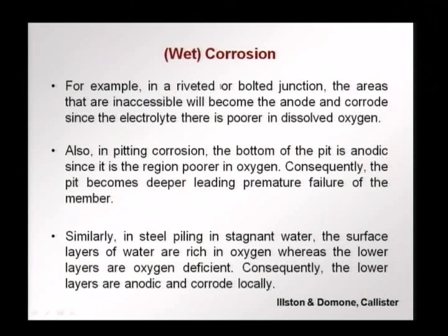Similarly, we find in sheet piling with steel in stagnant water, the surface layers are richer in oxygen, whereas the lower layers are oxygen deficient. So, what we find is at the top we need not see any corrosion occurring, but just below the surface, not very much below, but just below the surface where you have lesser oxygen, the layer of steel becomes anodic and starts to corrode locally. So, again requiring inspection and proper design such that areas which could get less oxygen are protected against corrosion and inspected periodically.